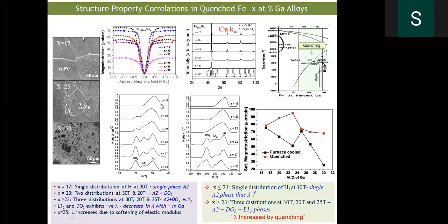And based on the magnetostriction study also, we have found that the quenched alloy is found to have high magnetostriction. This is basically because the single phase material shows high magnetostriction, because DO3 and L12 have a negative magnetostriction. So to have the single phase, we went to the phase diagram in this portion and tried to quench the alloy from high temperature. We heated up to some 1000 degrees centigrade. When we quench the alloy from this 1000 degrees, we could essentially retain the high temperature phase, and we could get a high magnetostriction.